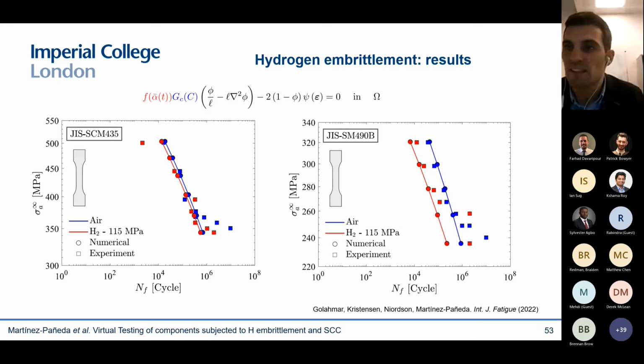Let me jump now to fatigue before I move to the corrosion part. We can also extend this framework to deal with hydrogen-assisted fatigue. So the idea is similar. You add a fatigue degradation function that degrades the toughness in addition to the degradation of the hydrogen concentration. This is a paper that we just published. And there's many interesting things that we can do with this.